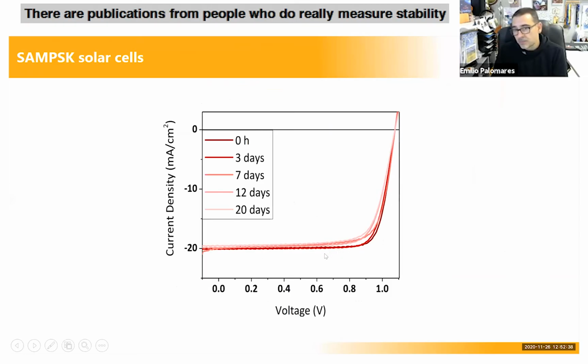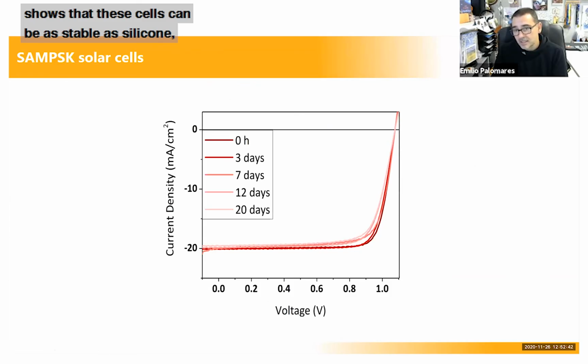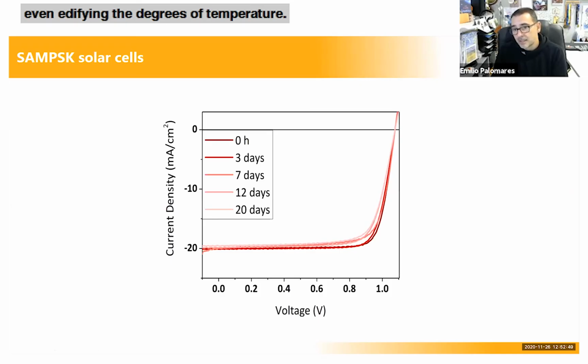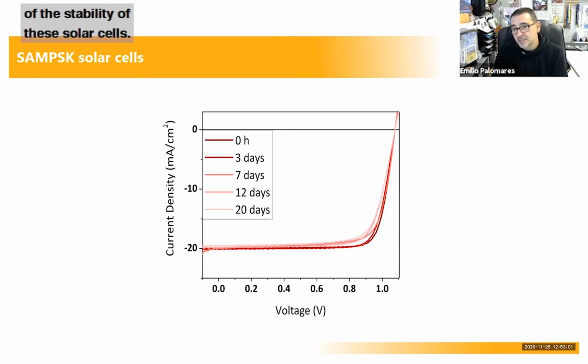There are publications of people who do really measure stability that show that these cells can be as stable as silicon, which means more than 1,000 hours at one sun, even at 85 degrees of temperature. So if you want to know more about this, you can check the bibliography by the group of Henry Snaith or a group of Ted Sargent or Antonio Abate. They are the three main leaders in terms of the stability of these solar cells.